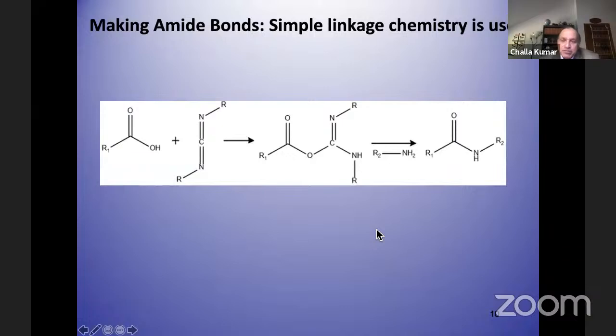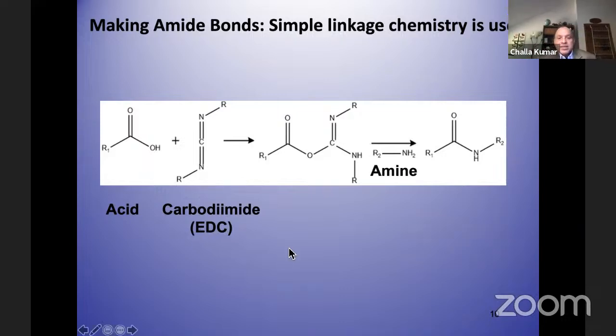So the chemistry we do is very, very simple. We take an acid, RCOOH, and activate it with a carbodiimide. A carbodiimide is a carbon with two imides on either side attached to it. It reacts with the acid to form an unstable intermediate, an acylisourea, and then that is substituted by the primary amine, making an amide bond. EDC is the abbreviation of the water-soluble carbodiimide we use in my lab, so I will use that abbreviation. Any primary amine can react with it, and then you make an amide bond. And so that's the amide bond.